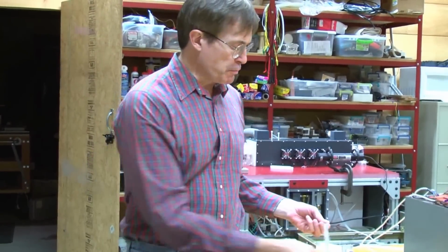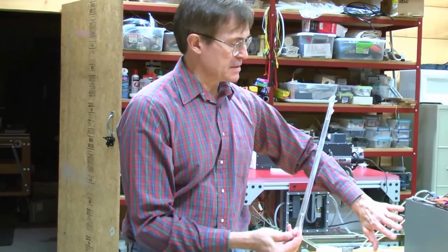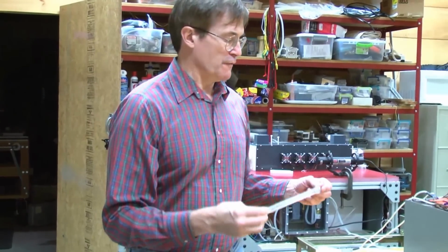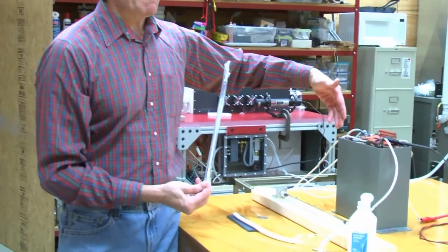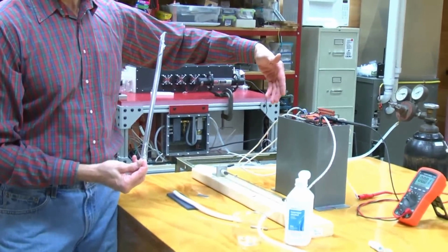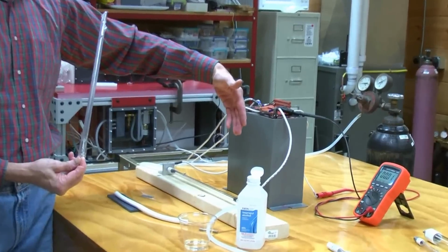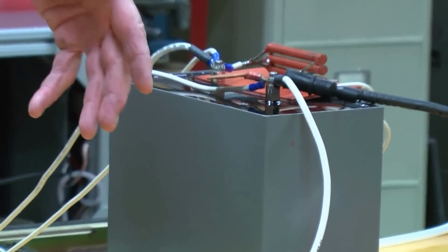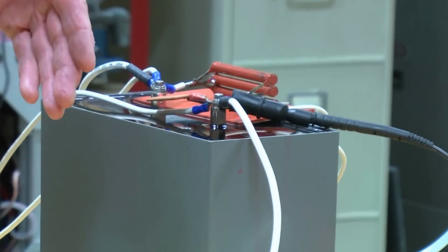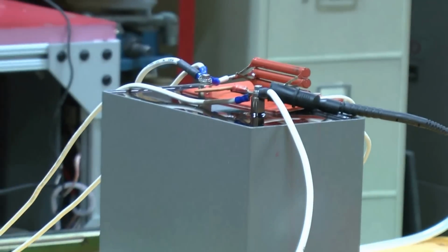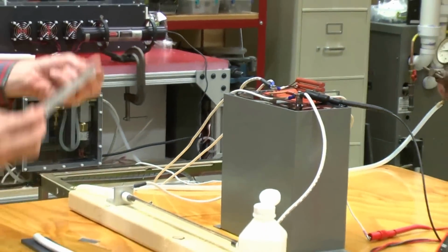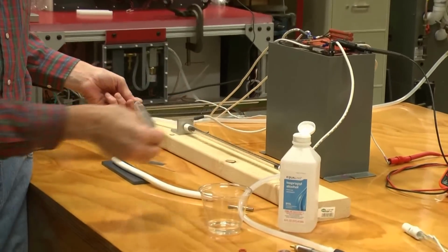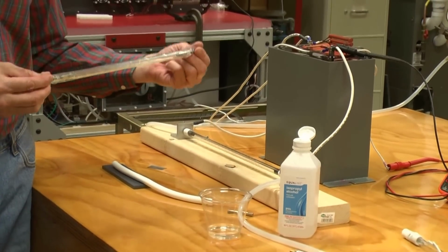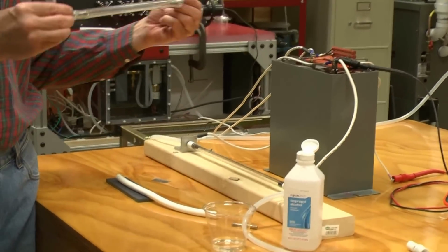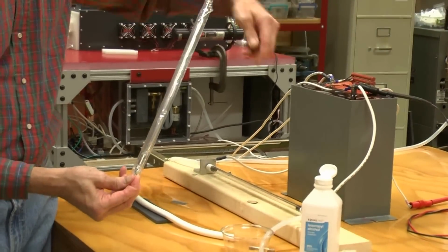So what happens is when you put one of these tubes in this capacitor system, you'll find that the capacitor has a ringing frequency of about 100 kilohertz. It's got a discharge through, say, a spark gap or a dead short of about 5 microseconds. You take this particular scientific grade flash lamp, high pressure xenon, put it into this jig, and it will discharge in about 60 microseconds. It's the major impedance of this electrical system.